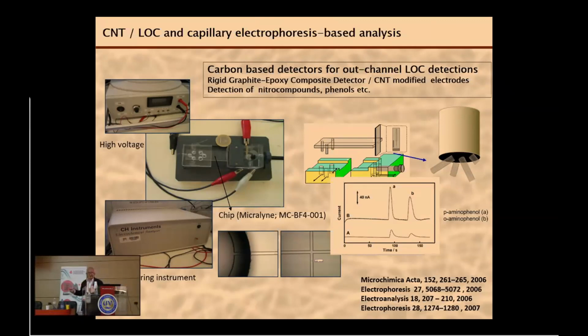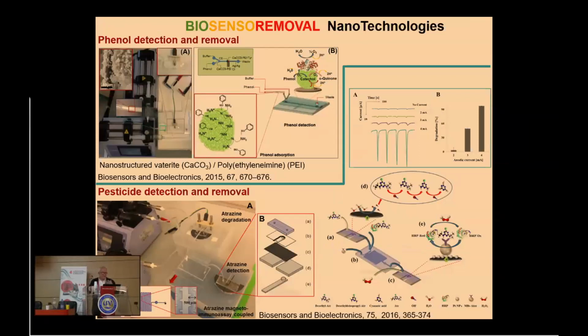And this comes from a project, Life on Mars. We wanted to see how we can bring these devices for astronauts to use and check, for example, samples directly if there are some amino acids, etc. Of course, they should have some electroactive properties. And we used carbon nanotube modified electrodes, and you see here different amino compounds were detected very fast using a 3 to 5 centimeter capillary instead of the 70 centimeter electrophoresis capillary that we use in a conventional laboratory. So this is also very interesting, and some more complicated things.